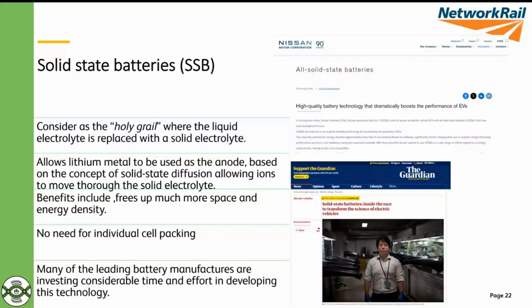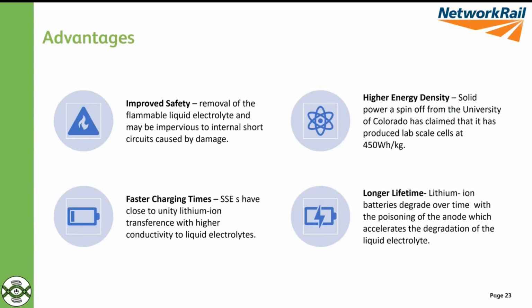So if you can remove all that graphite, you can remove the individual layering for the cell packaging, which is a big issue, and you start to get some real benefits in being able to move that forward. One major problem with the technology is you've still got this issue of cycling, stripping the lithium metal, depositing it, and then putting it back on, and that continuously happening, which can cause problems in terms of void formation within the solid electrolyte, cracking of the solid electrolyte, and the formation of dendrites as well. So there's a number of challenges with the technology.